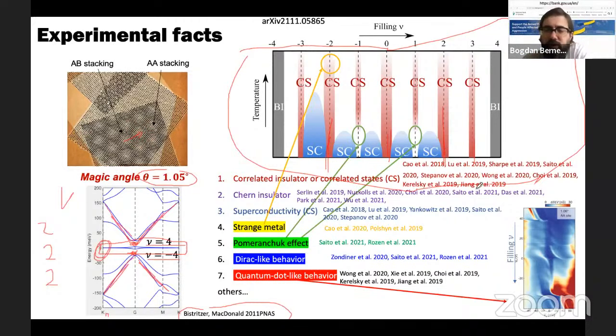Moreover, in between these insulators, you see superconductors, and this is actually a kind of phase diagram, which is reminiscent, obviously, of the cuprate phase diagram, except now you have the tunability that you didn't have in the cuprates to tune this electron number and look at the properties of the system in a sample that is the same, rather than dope it with different dopants and look at different dopings such as you have in the cuprates. And moreover, there's all kinds of other behaviors, such as strange metal behavior at large temperatures. Then in STM, there's quantum dot behavior in tunneling studies. And then some of these insulators that you can see here are actually Chern insulators, so the correlated topological insulators, or at least close to correlated topological insulators, as we'll explain in a little bit.